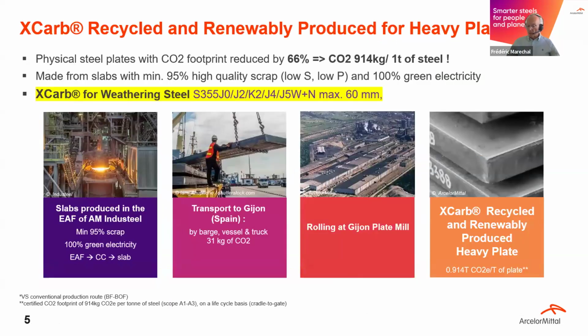So, and this is also something that you have already heard. So we are actually very proud in ArcelorMittal to be a pioneer and also among the best in class for the low CO2 steel, in this case for heavy plates. So what we have achieved in our mill in Gijón for heavy plates is something significant. So we managed to improve the carbon footprint with very impressive figures. I won't explain it again because my colleague already did, but just to give you a short information on this. So we managed to reduce the CO2 emissions by today by more than 65%.